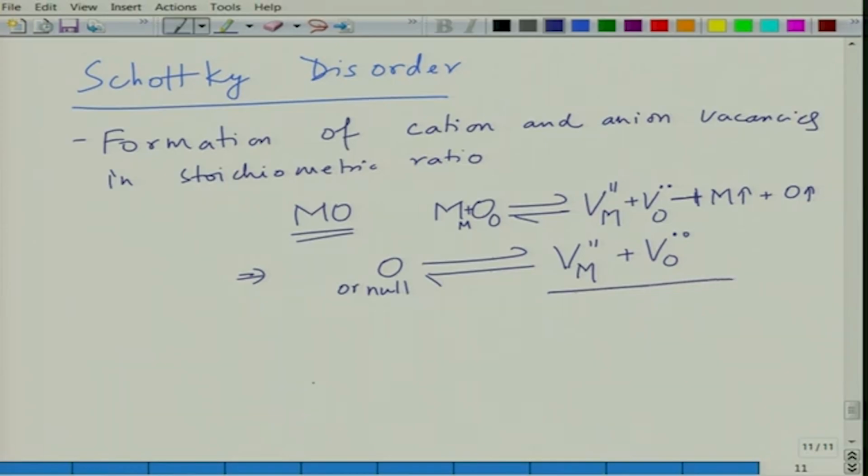What this means is that both metal and oxygen have to leave the system. So, this generally does not happen in the interior of the system, it happens at the surface. That is why these defects are usually found there, because the metals and oxygen have to diffuse out of the system, and this diffusion takes energy and it is more plausible at the surface than in the interior. So, these defects generally form at the surface.